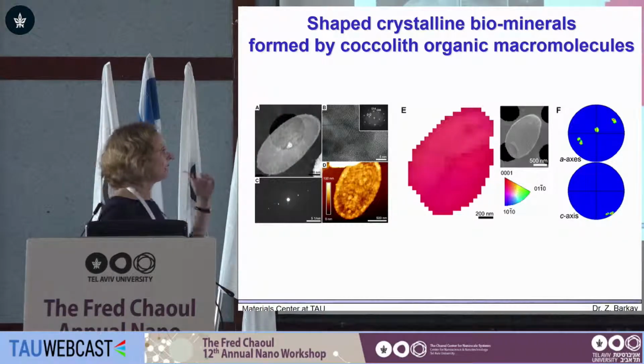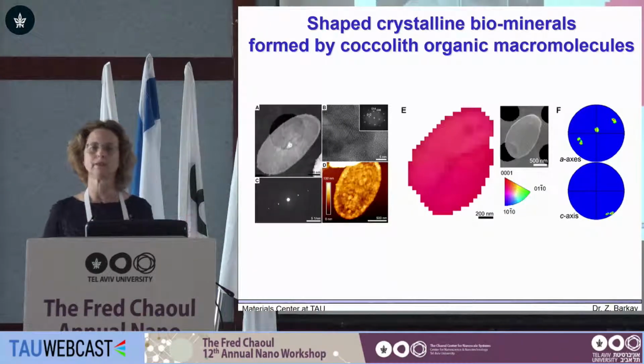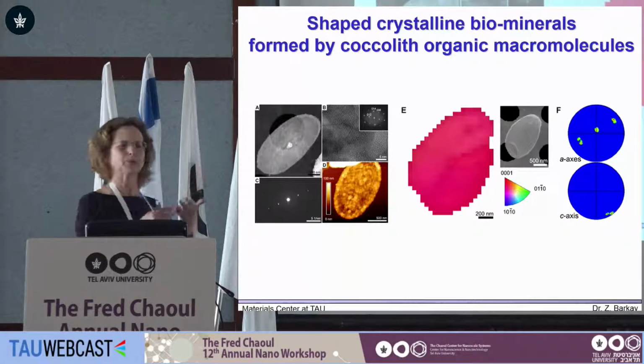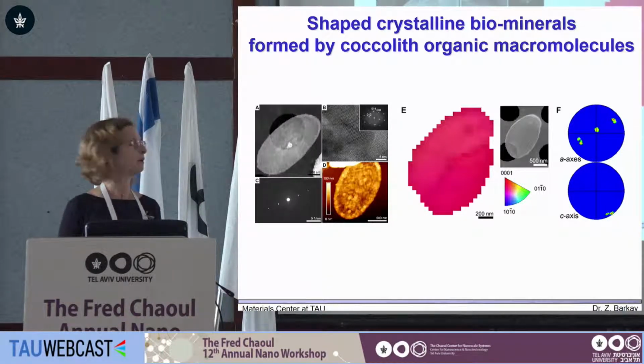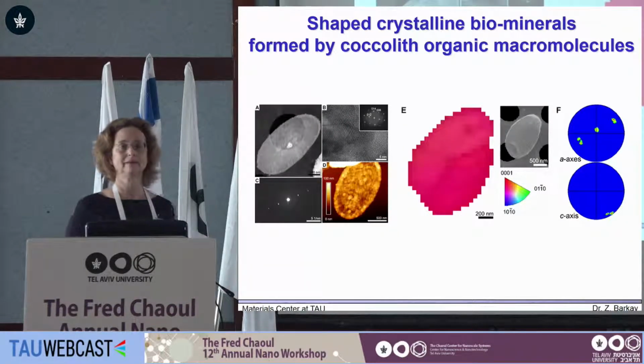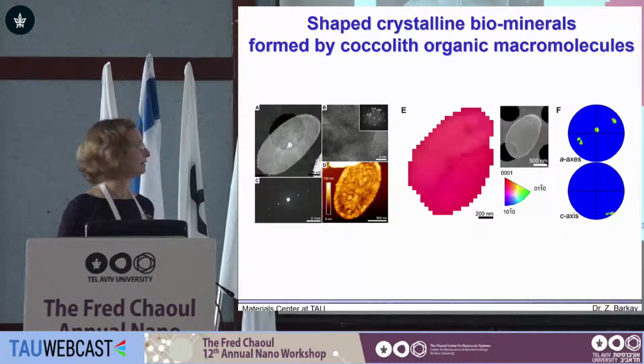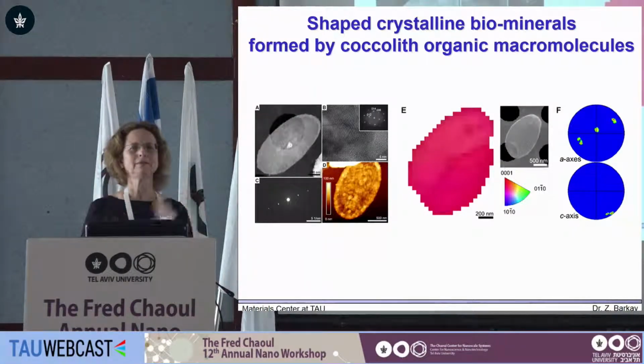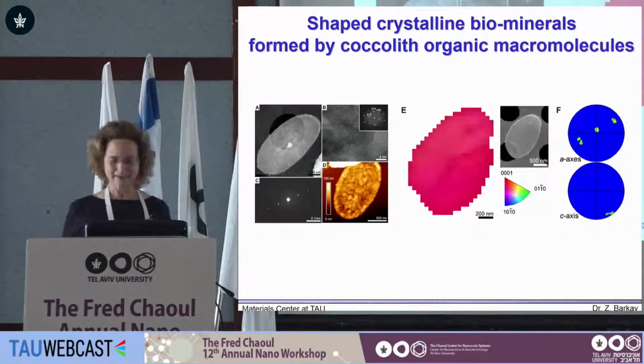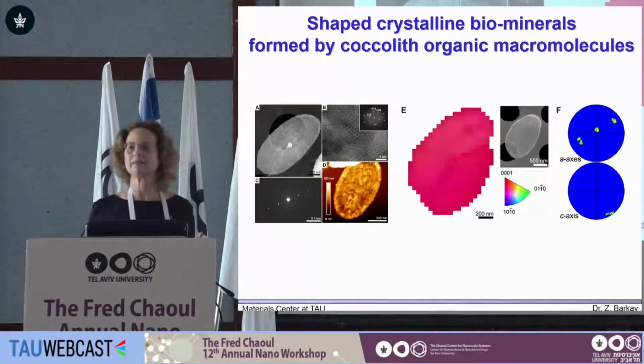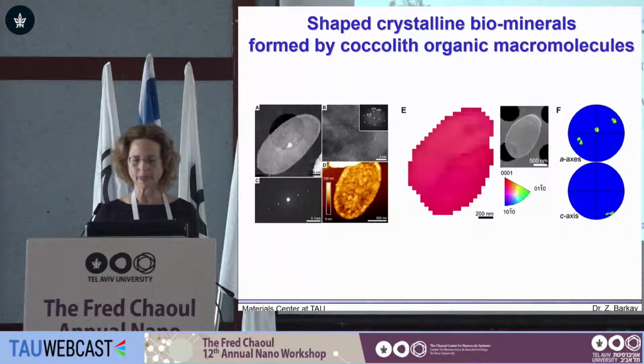What I want to emphasize here, this is the pole figure showing the orientation in plane. The step size for identification was 70 nanometers, but we could reduce it to 10 nanometers. This is the appropriate length scale for doing this TKD, and this is the advantage of TKD. But as I said, it is sufficient, it is actually very excellent, and that was where we stopped.